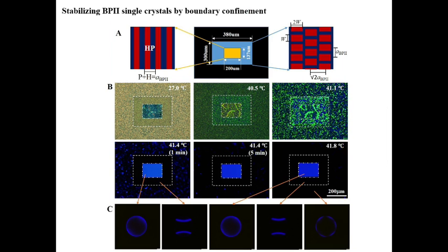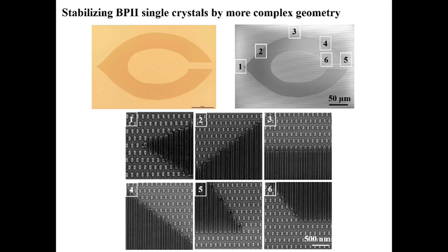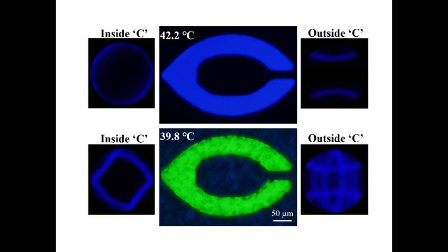So even though you ramp up those strap patterns with the rectangular pattern, you're going to have very distinguished lattice orientation within the black area and blue area. Even though you can make the pattern area not just a straight line but more curved pattern with all those small features, we found that the crystal forming on the system can closely follow all the curvature on the pattern, replicating the geometry of the pattern you print and forming the single crystal wherever you have the pattern to control it.